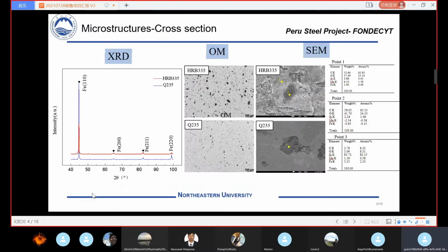Then we measure the microstructures. Firstly, the microstructures of the cross section. This figure shows the XRD results. From the XRD results, we found both the HRB 335 and Q235 are composed of ferrite. We can just observe the ferrite peaks in these two alloys.